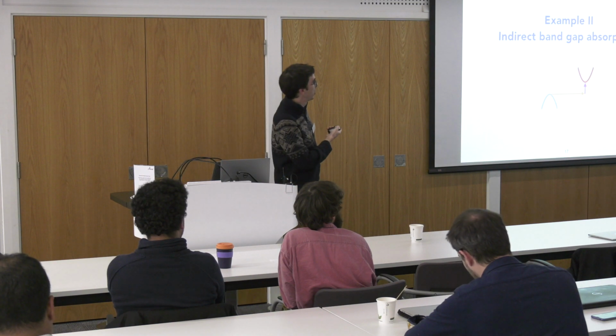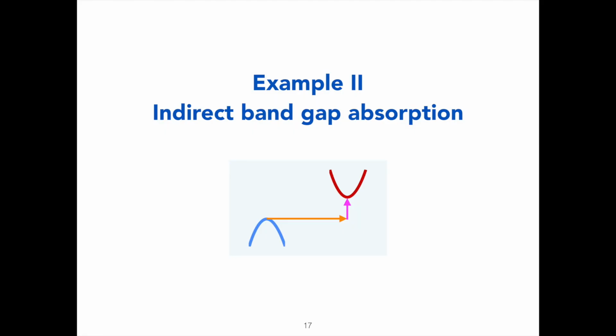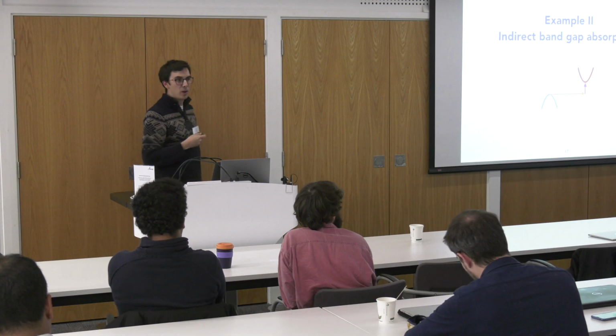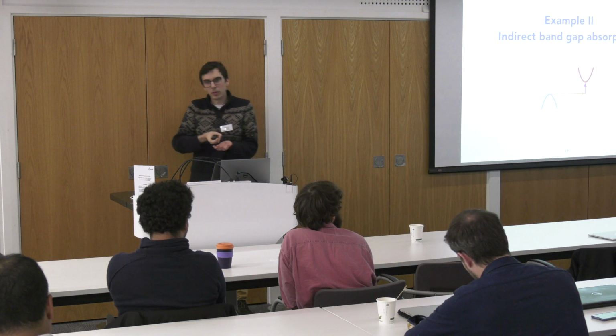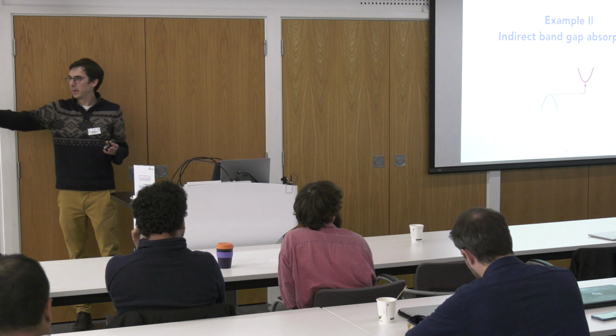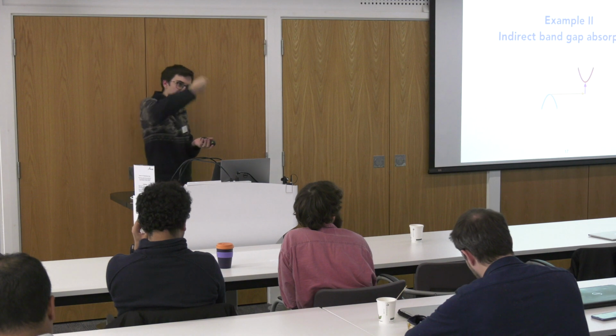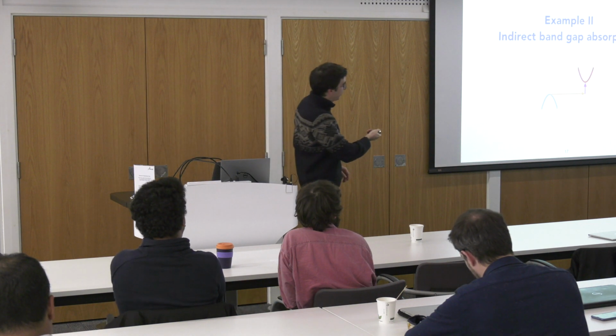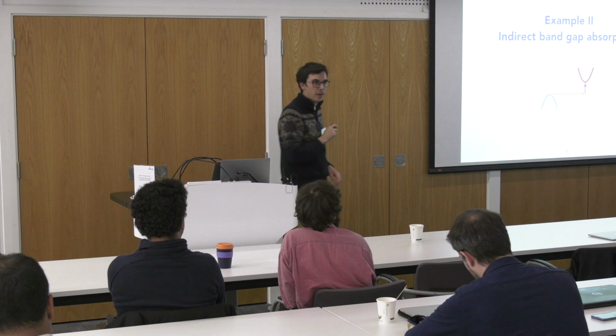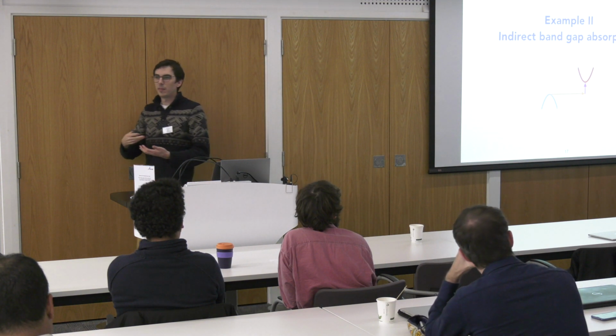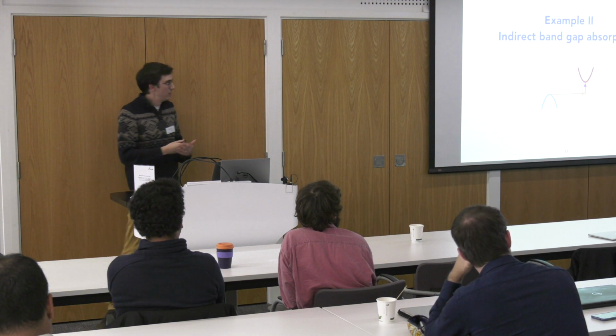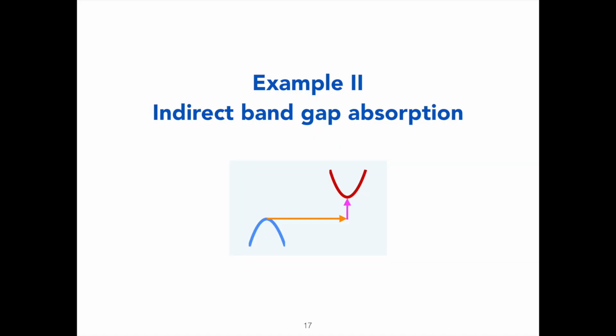So the first example has to do with indirect absorption. I might have a material with the top of the valence band here in blue and the bottom of the conduction band here in red. If I didn't have dynamic disorder, then a transition between one and the other would not be allowed, because when a photon comes in, it brings in a lot of energy but almost no momentum compared to the size of the Brillouin zone. So it only induces vertical transitions. A photon by itself could not induce a transition from here to here. In order to induce such a transition, I need to provide some momentum, and this momentum can come from dynamic disorder. That's what a phonon does here.